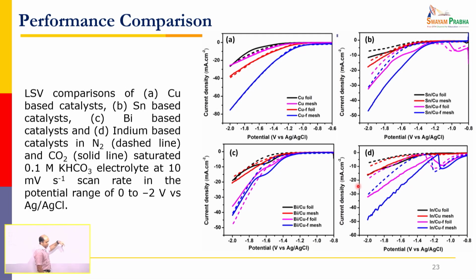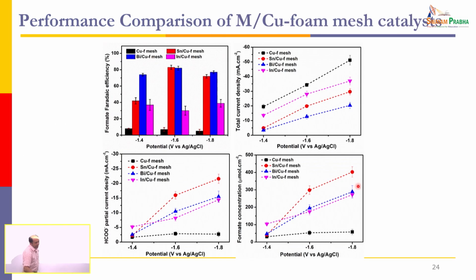You apply a particular potential for 1 hour or 2 hours, and then you monitor the product, how much product is formed in 1 hour and 2 hours. So we have done that for 1 hour. We applied 1.4 volt, and here four materials are compared. You have a bare copper mesh, then a tin deposited one, a bismuth deposited one, and an indium deposited one.